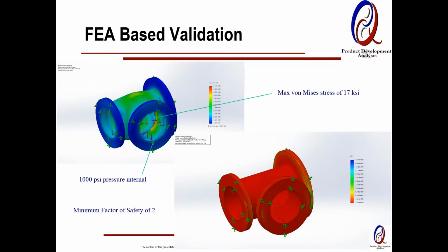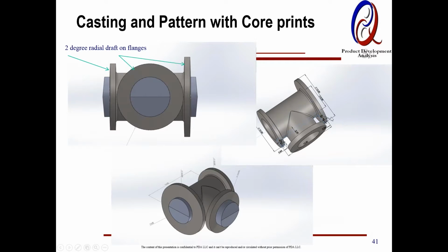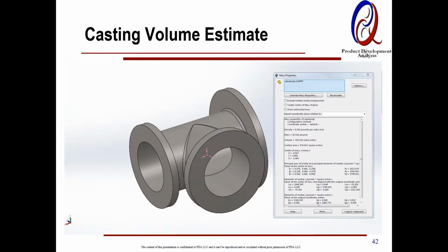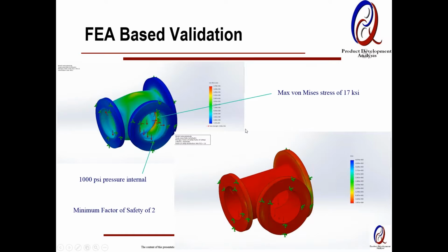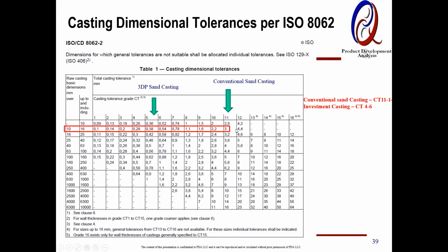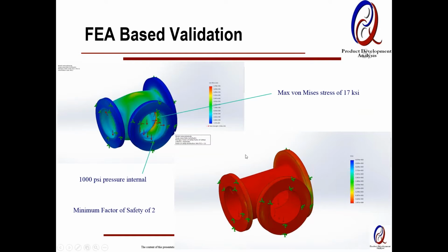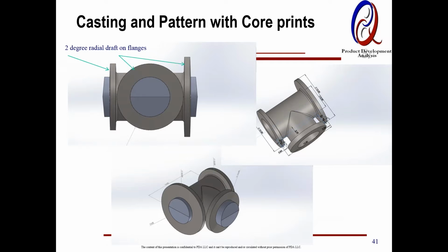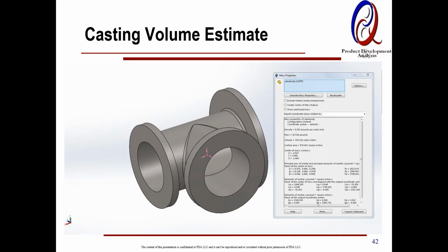So simple stuff means your current casting wall, and this is the current design. I don't know if you can see it clearly, but the wall thickness is given here, and with the tolerancing, whatever is the design wall, 12 millimeter plus at least 3, so 15 millimeter, whereas you can go 12.38 or 12.4, and you will still be okay with the minimum wall thickness requirement. And just by doing that simple trick, we validated to make sure the stresses don't go out of range. And this is the conventional, this is the volume.